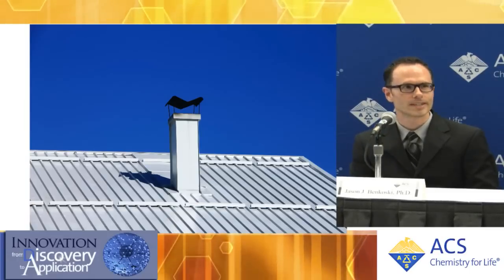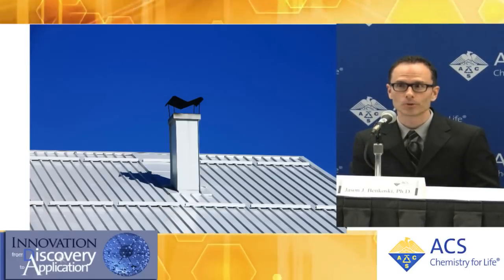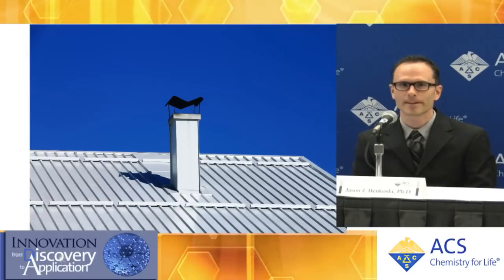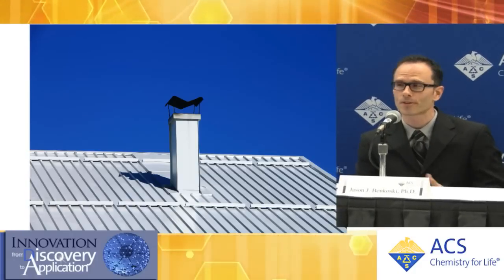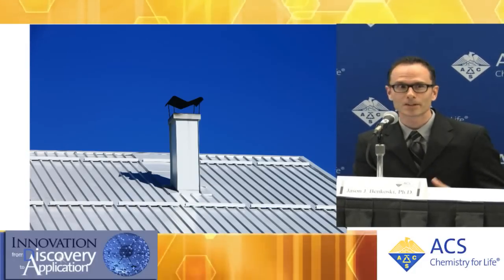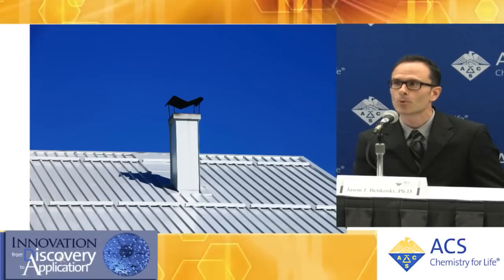So just to give you a little bit of background about our research on this project, one of the things that we're really trying to do is to protect structures against the damaging effects of sunlight. A lot of the time with sunlight, you think about UV degradation, but one of the things that I think people forget is that just the heating by itself can cause a lot of damage. You think about something like corrosion, for example. If you put corrosion inhibitors in your paint, in order to protect steel or aluminum, you'll be very happy if you can decrease the rate of corrosion by a factor of 10. But just imagine now if, because of direct sunlight, your surface raises in temperature by 30 or 40 degrees Celsius, you might increase your rate of corrosion by a factor of 16 or more just by the fact that it's hotter.